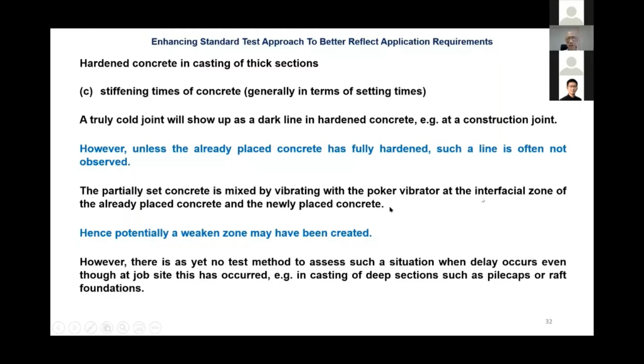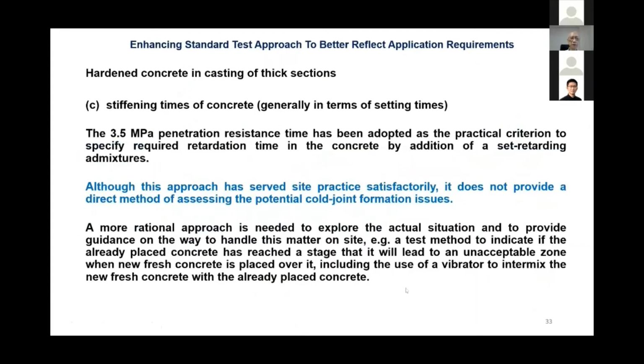Many of us in practice will unfortunately occasionally face this issue. So what we actually created is not a cold joint, but a weakened zone. So this is of interest, if we have a method to decide what the tolerance is, because every time we design a concrete, there is always a safety margin to give us a lot more benefit than the minimum that we require. So we need to make use of that side of decision making. So 3.5 is taken as it is. Okay, let's accept it for the time being until we have a better criterion.